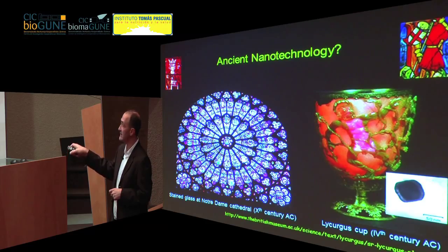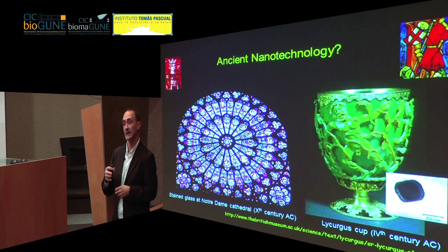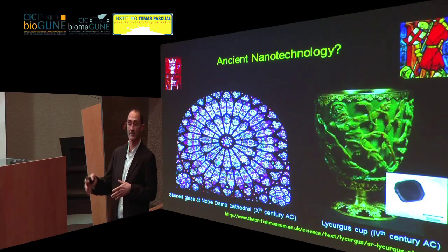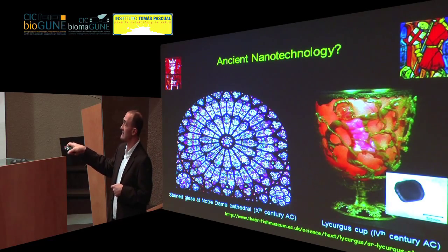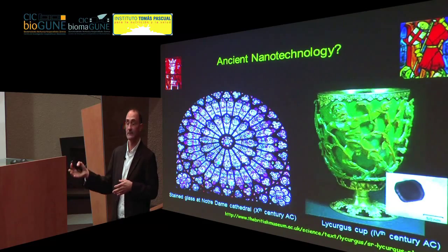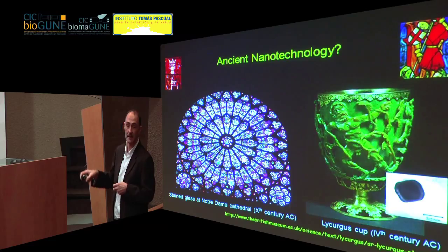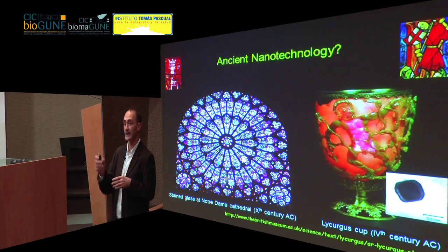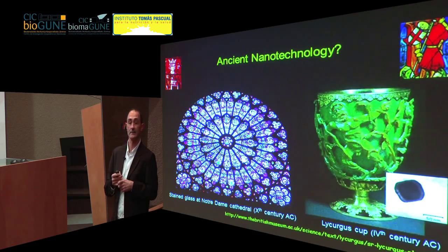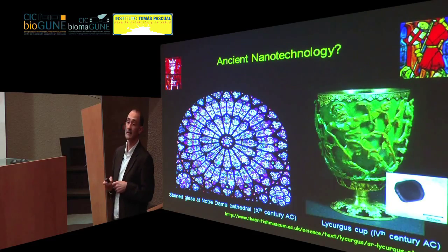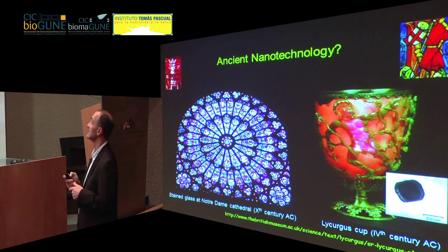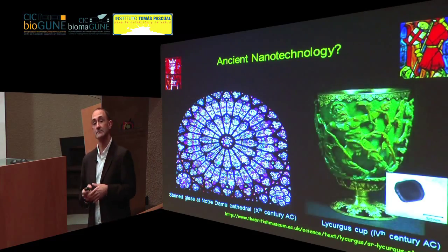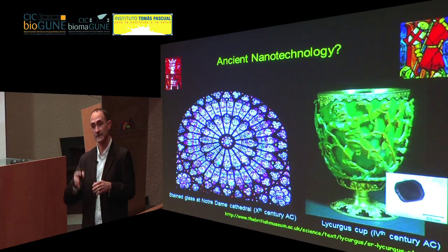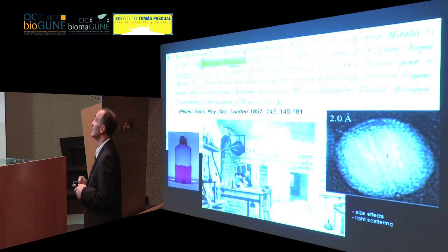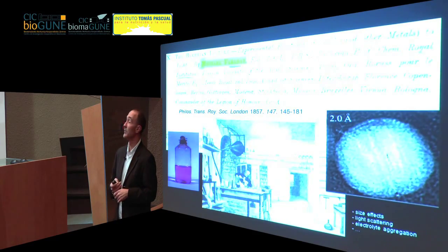The reason why we still see colors in these stained glasses is that the dyes are actually inorganic pigments. And the reason that we can only see the colors from the inside of the church and not from the outside is that the pigments are so small, nanometer scale, that they can absorb a lot of light, but they cannot scatter much. So you don't see the reflected colors. These are nanoparticles contained in the glasses and providing these really nice colors. Not all of them are metallic particles, but they are all particles of very small size that have specific absorption and provide this color.